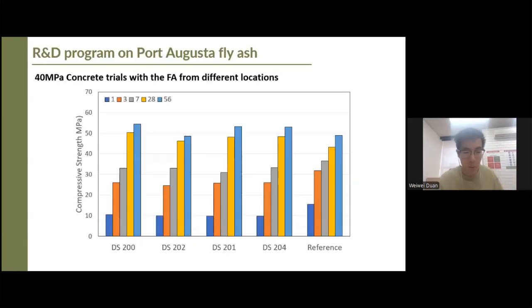Okay, so all this testing indicates that the processed fly ash could be suitable to use as SCM in concrete. To prove that, we put it into making 40 megapascal concrete trials. So that is the result of the fly ash from different locations. And you can see that the early strength does not increase as fast, because fly ash is a pozzolanic material.